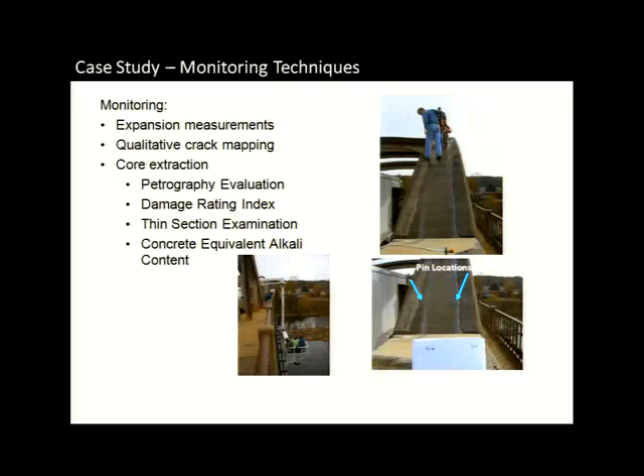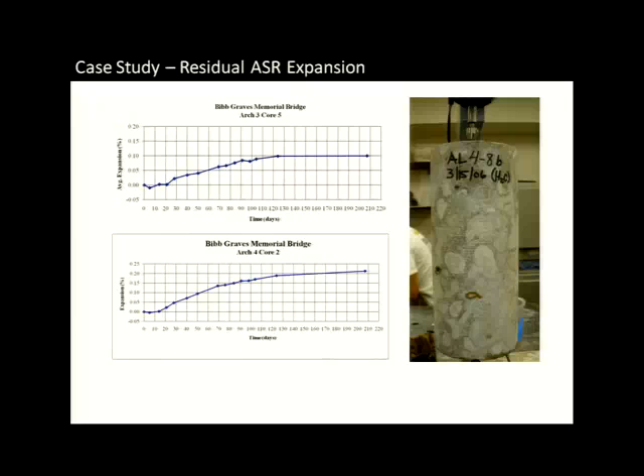And then I mentioned a few of the other techniques that we can use to determine what's going on inside the structure once we take cores out of it. So I'll just show you, here's a picture of one of the cores that came out of this bridge. This is a core from Arch 4. And what we do is we bring it back to the lab and we put it into a sodium hydroxide solution at elevated temperature to see if there's a case for residual expansion, to see if there's still enough reactive silica and enough alkali in the cement to drive the reaction further.